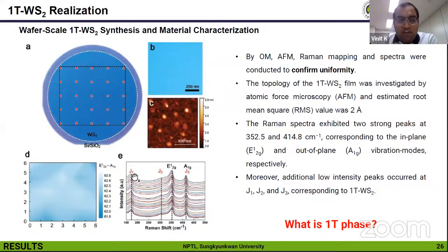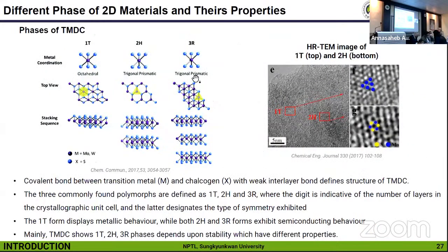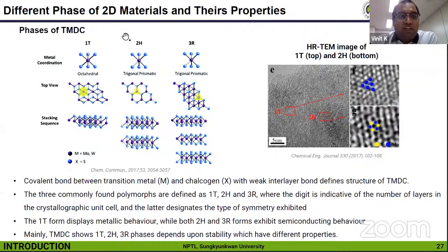But along with that, there are some other peaks such as J1, J2, and J3 peak, which are associated with the metallic or 1T phase of WS2. So what is the 1T phase, or what are these metallic phases? As I explained earlier, we will now discuss the phases.